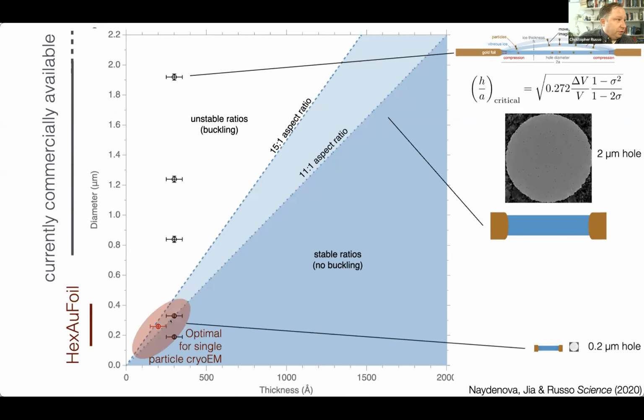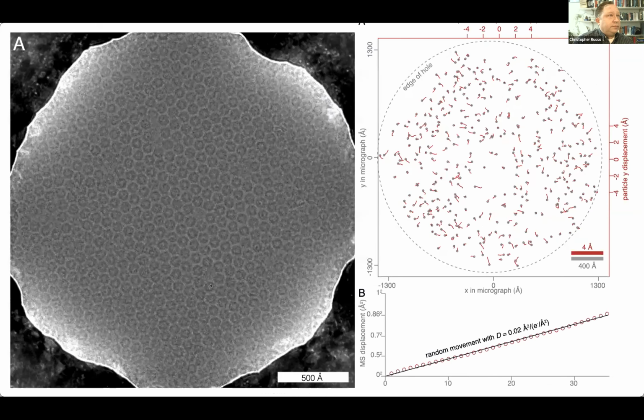But for single particle cryo-EM, where most of our specimens are around 200 or 300 angstroms thick, then it was very clear that we needed to have smaller holes in order to take advantage of this lack of buckling during plunging. And so here's what one of these holes looks like. So this is about 300 nanometers across, and it has a nice protein specimen embedded in it.